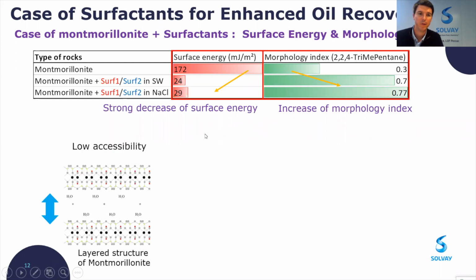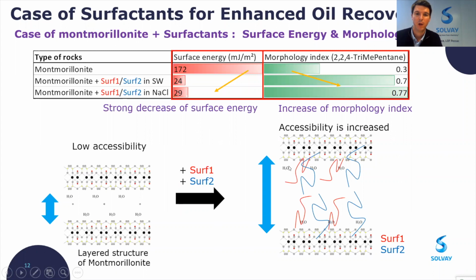We can explain that with, at the beginning, we have a layered structure of the montmorillonite with a low accessibility, as you can see in this illustration. And when we put some blend of surfactant, we have a strong adsorption within the layers of the montmorillonite, and you increase the distance between layers and increase also the accessibility for the different probes we have used for the estimation of morphology index. So it's very useful and interesting to estimate the different aspects concerning the surface properties and modification of the morphology.